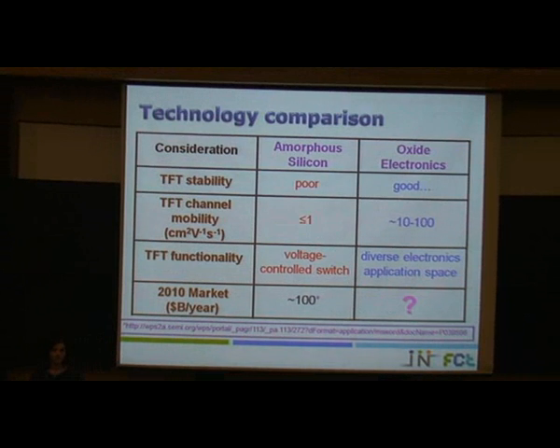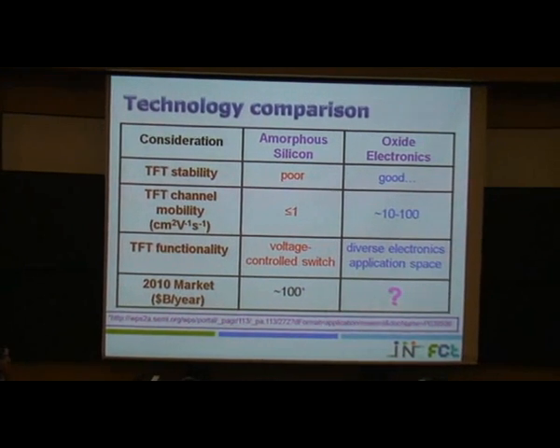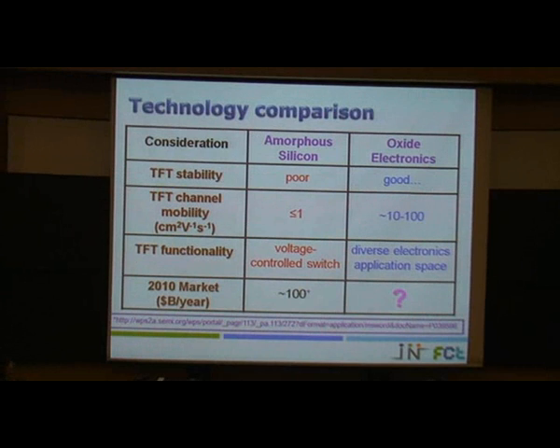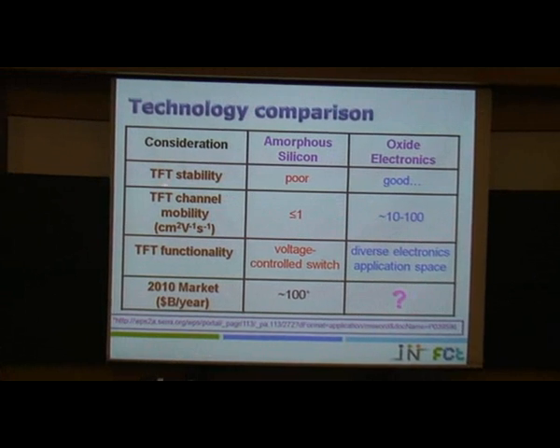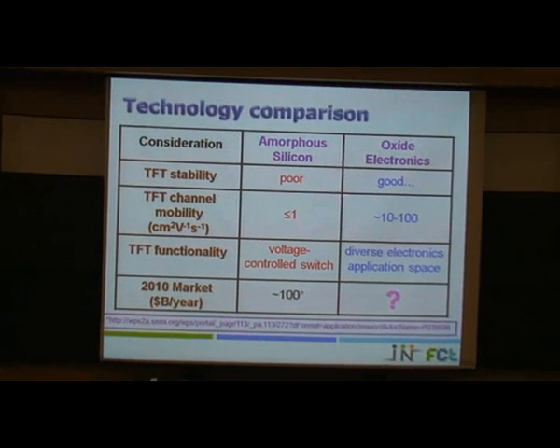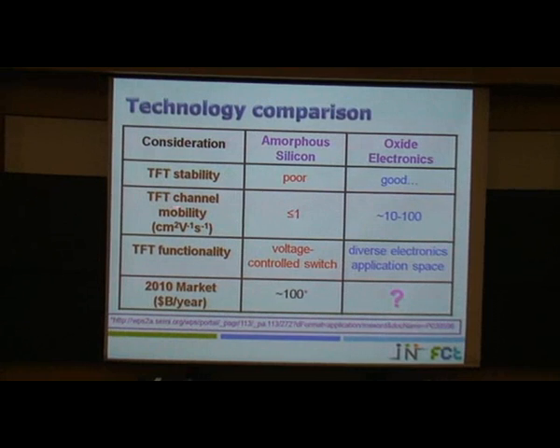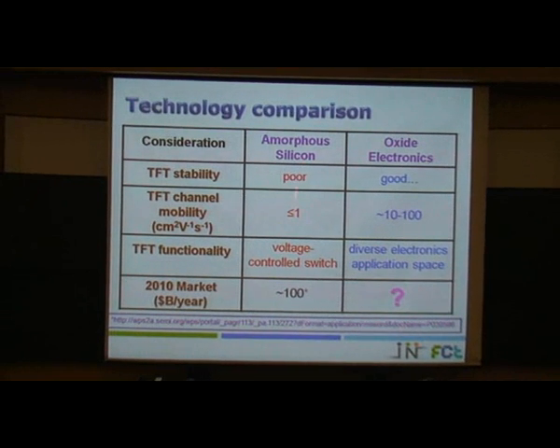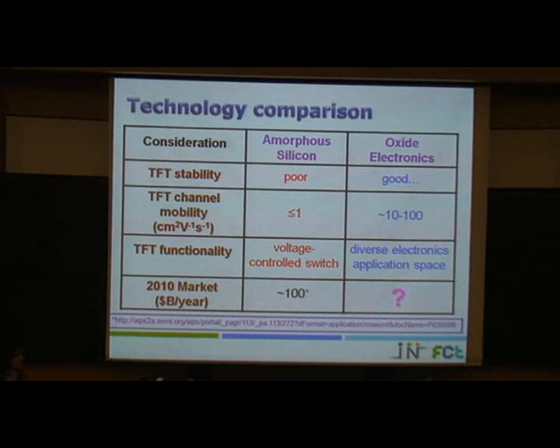And if we perform a comparison between the conventional technology, but mainly for displays, with the amorphous silicon or these oxide electronics, what can we say? Concerning stability, amorphous silicon is poor, oxide is good. The TFT channel mobility for amorphous silicon is lower than or equal to 1, and there is no way to increase this value. Here we can play. In some cases we achieved mobilities of the order of 100, so we are 2 orders of magnitude higher than in the case of amorphous silicon.